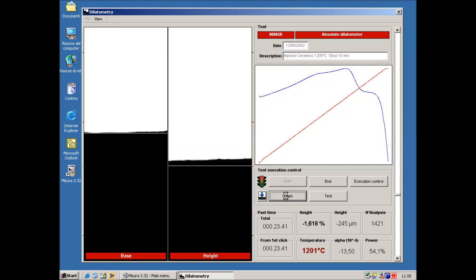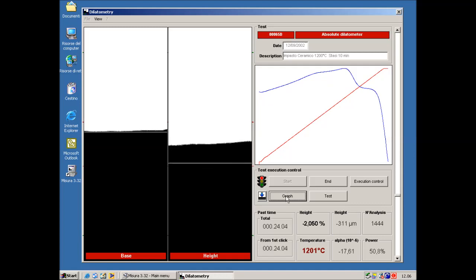The thermal treatment set for this test is made of 3 steps: heating up to 1200 degrees centigrade at 50 degrees per minute, holding the temperature of 1200 degrees C for a period of 10 minutes, and then cooling. The material is sintering very fast, and the step motor is working quite often to bring back the image in the center of the window.